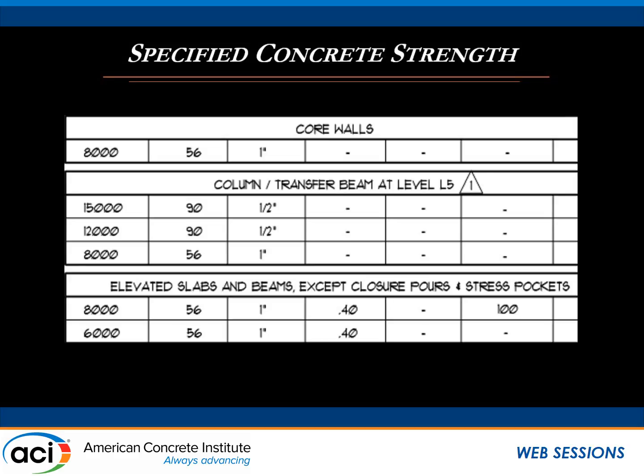The core walls, see, this building was designed before the recession, and we had different concrete strengths, and then it got sold to a new developer, and they added a floor. They jammed a lot of units in it, and they got rid of columns. So that's part of the reason why these columns are so high: less columns, smaller columns, because the average unit size was 700 square feet. So imagine you're living in 700 square feet as a family. If you go 3 by 3 column, it's a bit different than 20 by 30. So on the square footage.